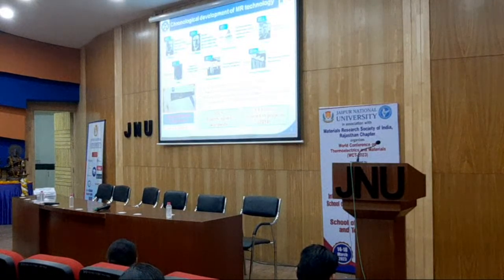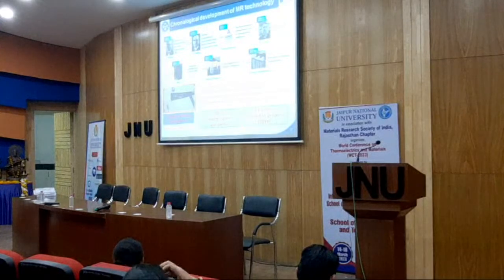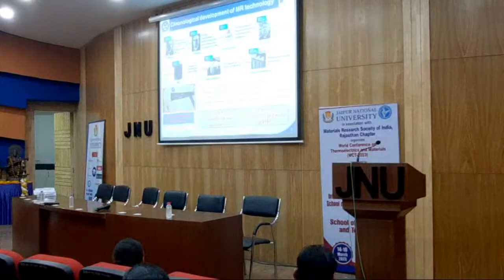So the main important thing about what has been developed to date: whatever refrigerators have been developed, they can generate around 400 watts of refrigeration power, and they can keep the internal temperature between 2 to 5 degrees centigrade for this simple material. That means the more you want to bring the temperature down, the more cycles it has to undergo, which I had explained in that topic.